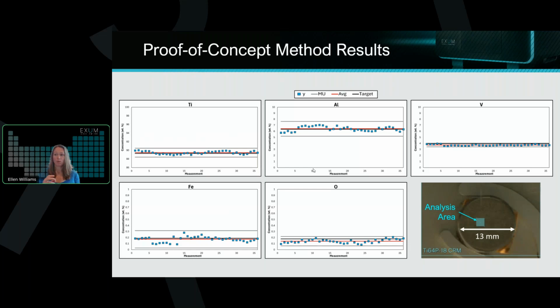So you can see that we have reliably quantified all of the elements that were included in this particular proof of concept method: Ti, aluminum, vanadium, iron, and oxygen. We can see that those average results that we're getting are quite close to that of the target. Again, we could get some more confidence in the target numbers that we have, so that we're not just using a reference material that has only been analyzed once. We could get more data points to have more confidence in that target number.